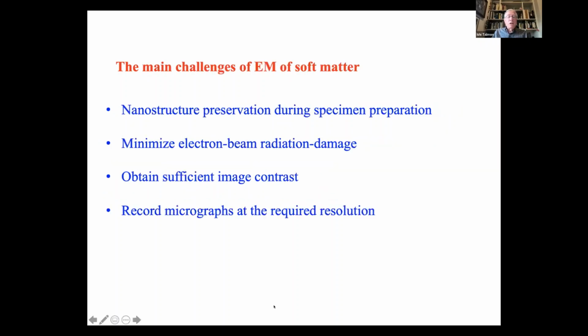But it's not very easy. First of all, we have to make sure that we preserve the structure during preparation. The electron beam that we use is a very strong ionizing beam, and if we are not careful, and if we use too many electrons during the observation, we actually destroy the specimen before we can record the image. So this is something that we have to take into consideration.